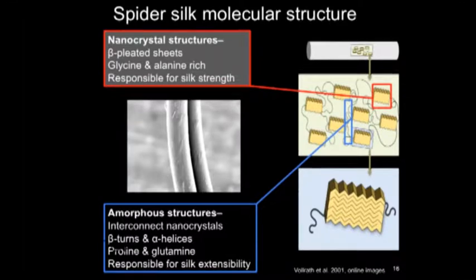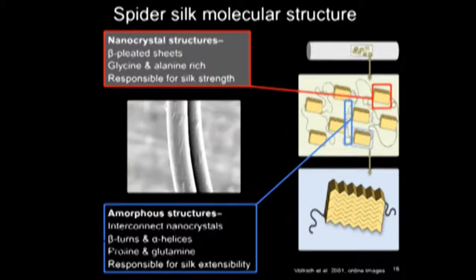The amorphous structures, which are sort of interconnected, semi-crystalline, kind of gooey almost, the more fluid-like structures, are composed of alpha helixes and beta turns. This is what gives silk its extensibility. So if you can imagine, you have a bunch of cords and bricks that are interconnected, and when you stretch them, it allows for a little bit of give, but most of the force gets dispersed to the strong crystals. So this is what gives silk its toughness attributes, as it's strong and stretchy.